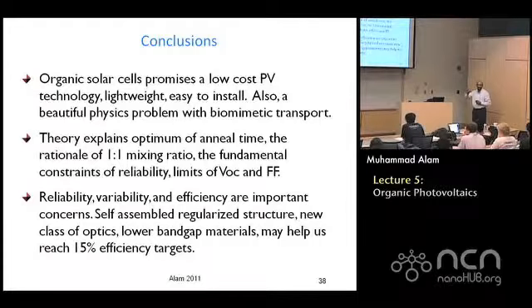So the best solar cell that you might say for organics is how much? Maybe 8.1% or so. But by the time the company wants to sell it, they cannot sell it to anyone. They sell it for bus stands and nice covers on the automatic, because it's not commercially viable. So in that case, they only get about maybe 3 to 4% efficiency. Very, very poor, nowhere near what it needs to be. Okay, but I suggested a few ways by which we can get to this 15% efficiency, and hopefully if we can do it, you'll one day buy your organic solar cells on your own. Thank you.